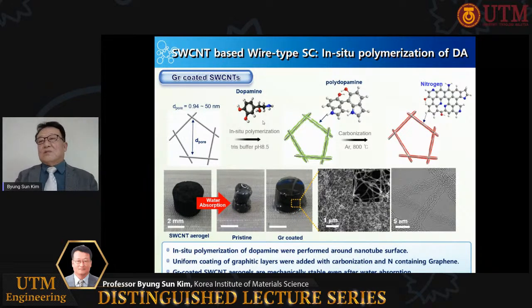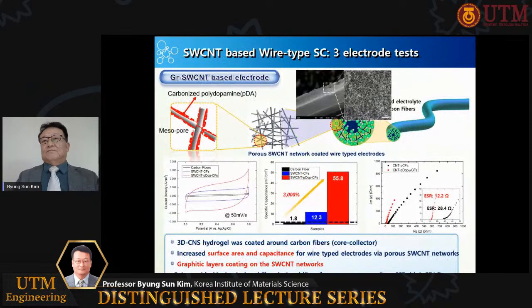Firstly, graphene-coated single-wall CNT aerogel was synthesized as shown in the photos. We carried out the in situ polymerization of dopamine around the single-wall CNT network as shown in the top schematic drawings. Uniform coating of graphitic layers was achieved with carbonization and nitrogen-containing graphene. Graphene-coated single-wall CNT aerogels are mechanically stable even after water absorption. Three-dimensional carbon nanostructure hydrogel was coated around the carbon nanofibers, which is the core collector.